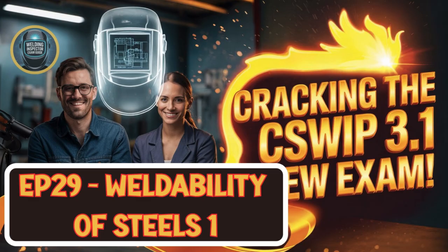Copper, maybe from contact with copper tooling or backing bars, can form films that remain molten even at temperatures around 1100 degrees C. Wow, that high. Yeah, so thorough cleaning of the weld joints immediately before welding is absolutely crucial. You want to prevent these low melting point films from forming in the first place. It's truly amazing how a tiny bit of dirt or grease can cause such a massive problem. Cleanliness is critical. What about the bead shape?